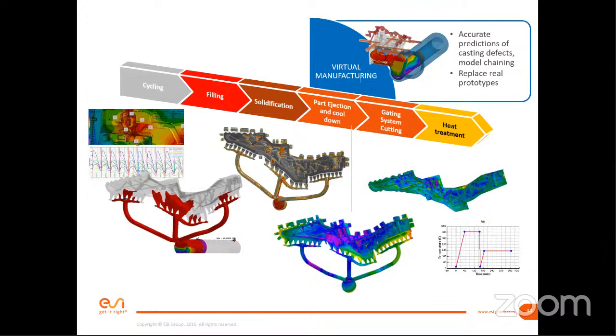So for this, the slides which I previously showed weren't enough, because we really need to know the thermal distribution of the die, what happened with the casting during the filling and solidification, but again, what happened with the die also, because it's heated up and then cooled, and so there is some kind of thermal cycle, which is problematic for the die. And we also need to analyze what happened with the casting after the ejection from the die. So what happened when the die is open and the casting goes out, and then some following operation. So we need to be able to describe it whole.